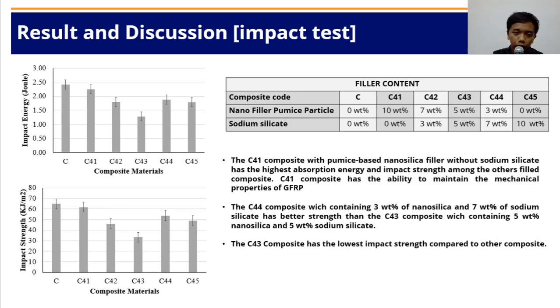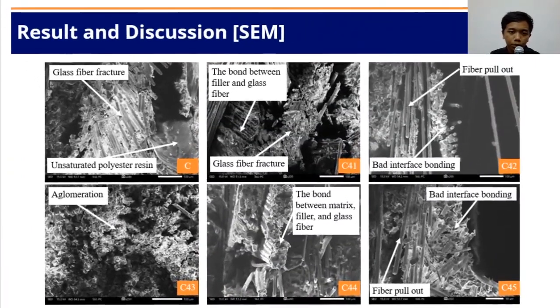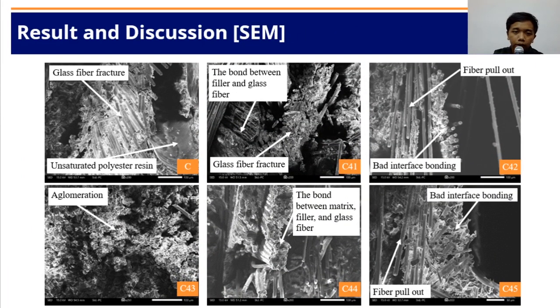Okay, let's move on to the result of the SEM observation. As we can see, the following images are the result of scanning electron microscope observation of the GFRP composites that have gone through impact testing. From the result of the SEM observation, the sample without filler, or C composite, shows a fairly good interfacial bond between the fiber and the unsaturated polyester resin.